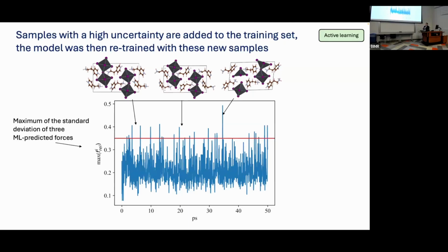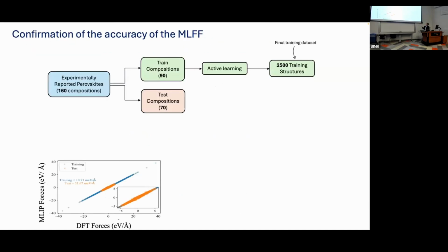So this is what's called the query by committee framework, where we use uncertainties based on disagreements between a committee of models. And if it exceeds a certain threshold that we have to set by hand, we grab these samples, we put them back into the model, and we train it. So that's our active learning loop. And at the end of this, we have this data set of 2,500 samples.